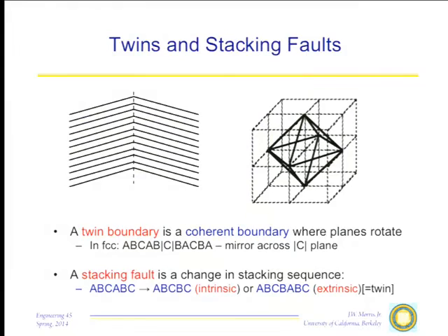What that tin cry comes from, tin is kind of a bizarre crystal structure. And even at room temperature, it tends to deform by twinning. It forms these twin planes, and these atoms all shift together. When they all shift together, they release energy. And the energy comes out in the form of noise. So you hear the bar complain as you bend it, and it's called tin cry. You'll get it in other materials. Zinc also tends to do that. So a twin boundary is something like this.